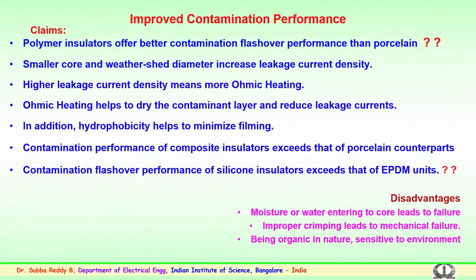The reason is that during crimping, even a minor crack formation or an overload because of the procedure being followed could later cause the insulator to shatter. These micro cracks may lead to the failure of the insulator or the fiberglass rod, and the line could be thrown away. So, this is a very important factor to be taken into consideration, particularly during the manufacturing stage.